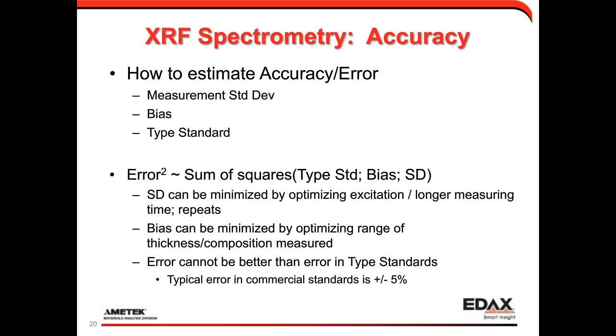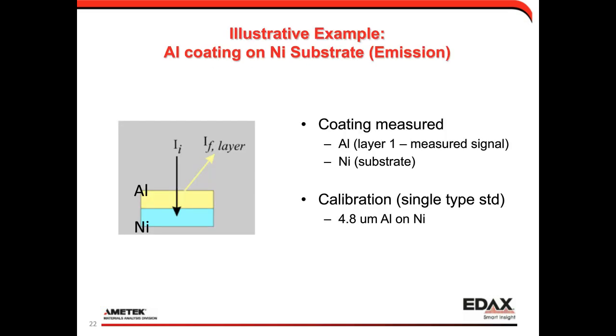Okay, some examples. This example has an aluminum coating on a nickel substrate. This I wanted to show you typically so you could see some of the different physics involved in making these measurements, either in an emission mode or in an absorption mode. So here we have a coating of aluminum on nickel, and aluminum is going to be the measured signal that we're measuring. And in this particular case, I calibrated it using a 4.8 micron aluminum foil on the nickel substrate. So it's a single type standard, single point type standard calibration.